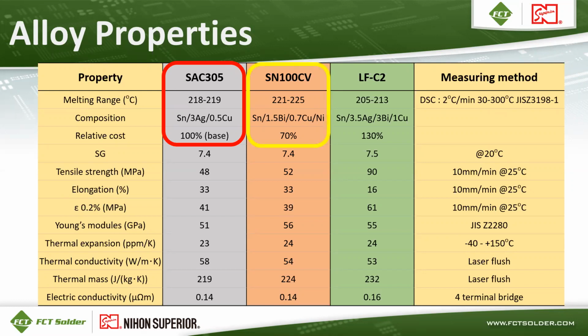SN100CV has a melting range of 221 to 225, so it's a little higher melting range than SAC 305, but it can reflow in a very similar profile to SAC 305. It contains tin, bismuth, copper, and nickel, and the cost of SN100CV is lower than that of SAC 305 because it does not contain silver, so it's about 70% that of SAC 305.